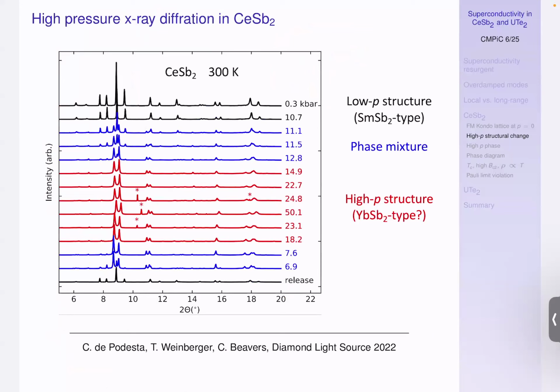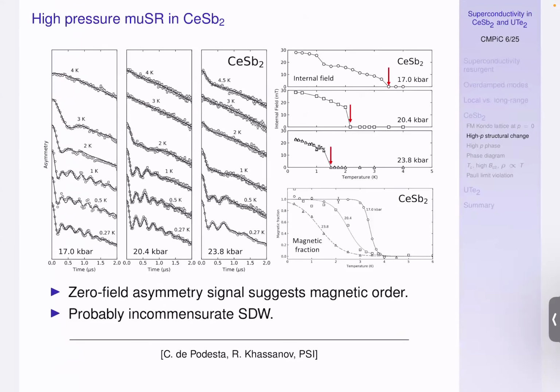So there's been quite a bit of work on resolving the high pressure structure. It goes basically to the structure that is also adopted by ytterbium antimonide (YbSb2). There are several possible structures for the lanthanide diantimonides, and we tried to match X-ray diffraction results as a function of pressure against different candidate structures, and the high pressure structure matches this one best. It's also what Theo's calculations suggest, that it should be the same one. Now, let's focus on the high pressure structure, because that turns out to be the really interesting one.